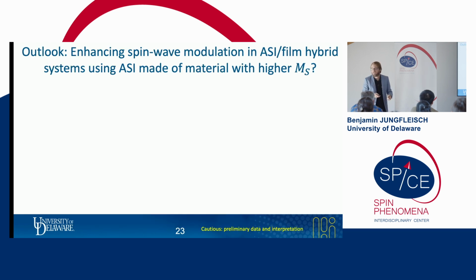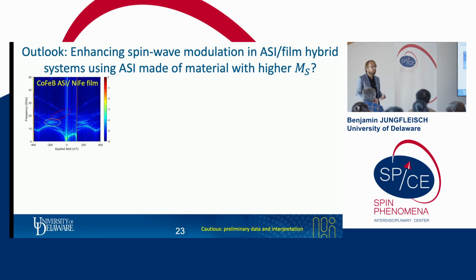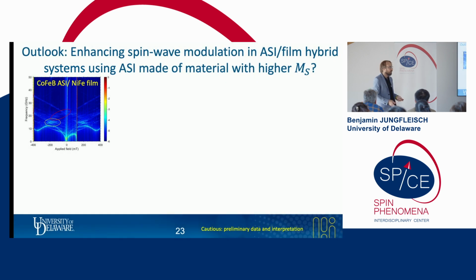Now, since I have still a few minutes, I just want to show you some preliminary data. So please take this with a grain of salt. How can we enhance this modulation of the artificial spin ice hybrid system? The way we thought we could achieve this is by using a material with a higher saturation magnetization to increase the stray field. So we did some experiments. I'm going to show you only the results of the micromagnetic simulations. So we use here cobalt iron boron as the artificial spin ice layer and put this on top of a nickel iron thin film. Previously, everything was nickel iron.